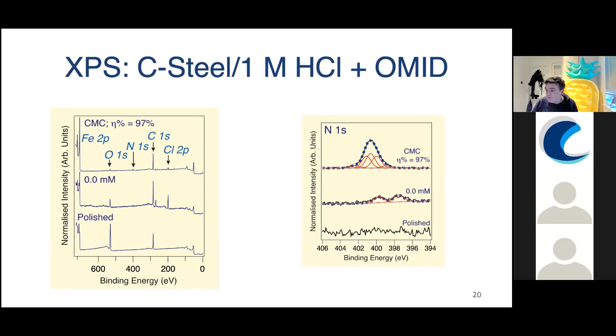Well, that's not working. Just one second. So here we have the oxygen signal, showing what oxygen is at the surface. And we can see quite a lot at the surface initially on the polished surface, because iron in air forms a thin oxide film very rapidly on the surface. So it's a thin oxide layer. When we immerse it in solution, it's reduced a lot. And once it's inhibited, it's rather small indeed. I'll explain what's going on there in a moment.